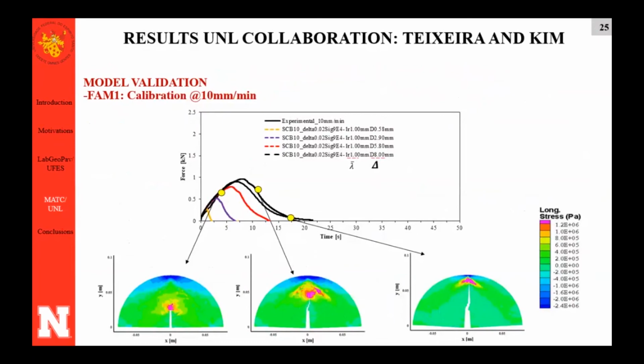So I took one test data from that paper that I use as a reference, with a loading rate of 10 millimeter per minute. And I used the delta value that was obtained from the analysis of the experimental data. And I also took the lambda bar from the experimental data. But I saw that the big delta value also needs another calibration. So I calibrated the big delta, the lambda I used the same based on experimental evaluation. And I calibrated the results, and you can see from the contour plots that the crack path actually follows what we observe in the laboratory.